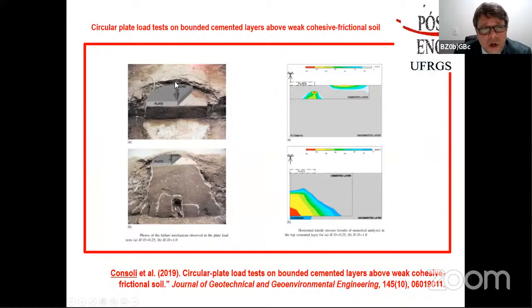So if you put a shallow footing on top and you load it, in the case where the thickness of the layer divided by the diameter of the plate is less than 0.5, we have the failure starting at the corner of the plate, which, numerically speaking, is through tensile strengths. And here we have seen exactly the same in the field. While in the case that the layer is quite thick, more than 0.5, we have the maximum tensile strength, and the failure starts at the bottom, exactly in the middle, on the symmetry axis, as shown here in the failure mode, which is also interesting. This was published in 2019 in the Journal of Geotechnical and Geoenvironmental Engineering from ASCE.